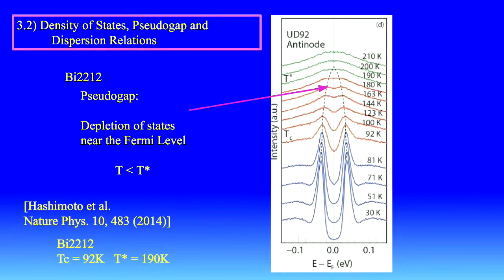So now the pseudo gap. What is the pseudo gap? If you take the density of states, when you lower the temperature under T star, the density of states is depleted near the Fermi surface, creating two peaks. And that's why it's called a pseudo gap.